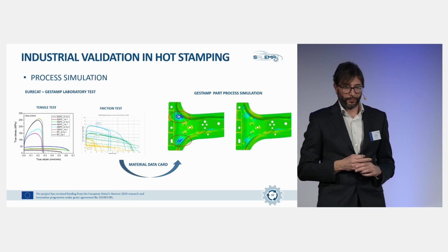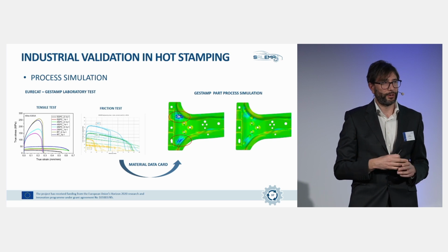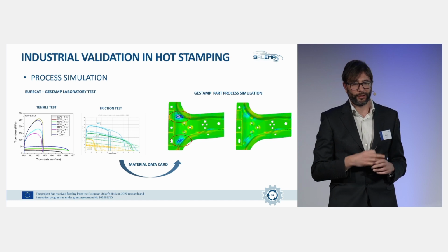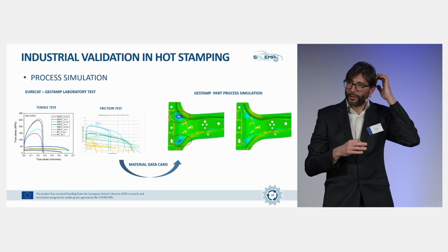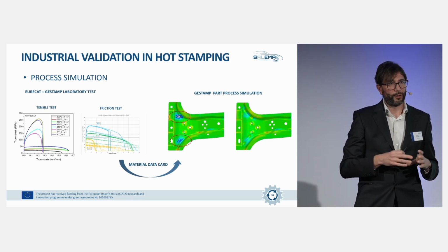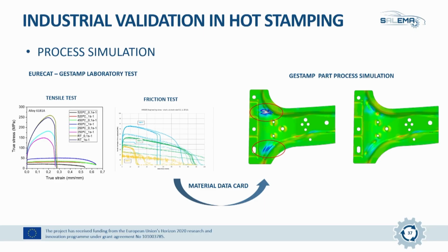Okay. So regarding process simulation, we characterized the properties of these new alloys at different temperatures and strain rates. Also, Gestamp did this friction test characterization that they bring in order to fit their simulation software model. In the first simulation, the one on the left, you can see some critical zones. With a small change in geometry, having a higher draw there, this problem could be avoided. So this simulation was useful in order to define this final geometry with these draws, in order to have a better final quality of the produced components.